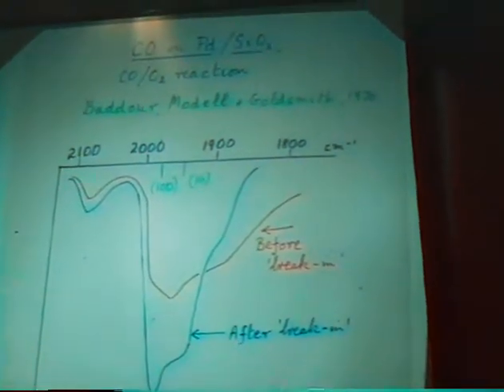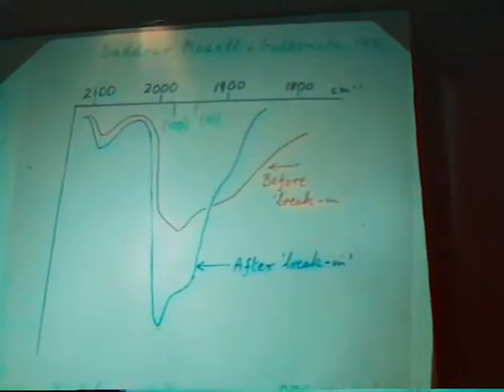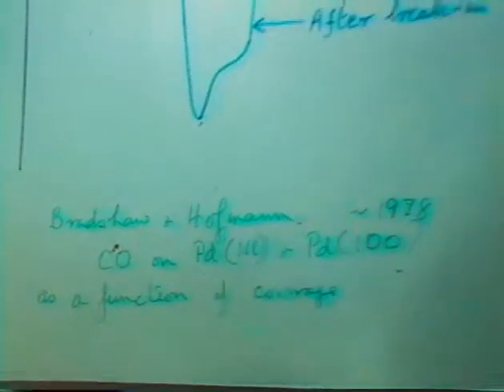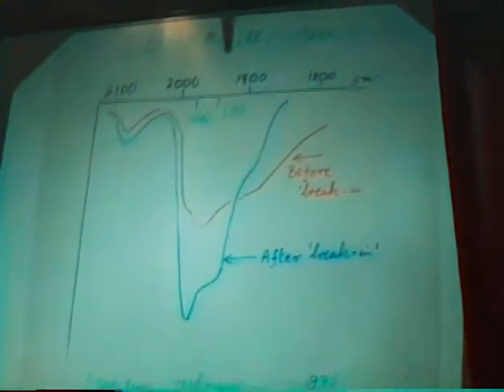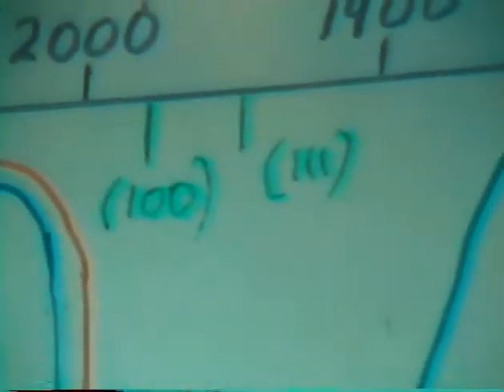And it was interesting to go back and look to quite an early paper in the literature on a finely divided palladium silica catalyst by Baddour, Modell and Goldsmith, I think at MIT, and to realise that within this broad contour of the bridge species, one can probably pick out those components which correspond to these particular crystal faces. These were the two different wave numbers associated with the two-fold bridge species at saturation coverage done by single crystal work, and you can see that they correspond to the two main features in the spectra of the adsorbed species. But the interest of this work was that they showed that the catalyst changed.